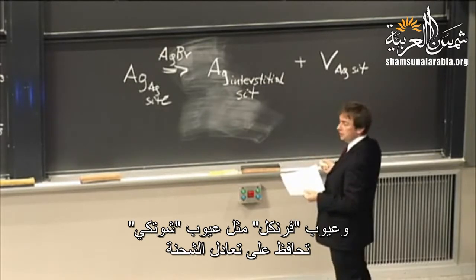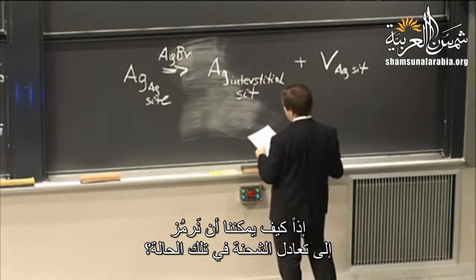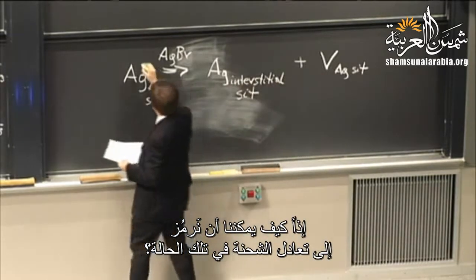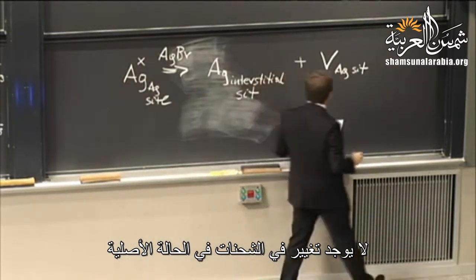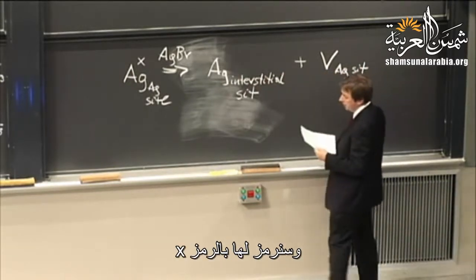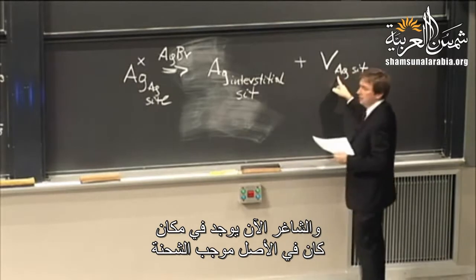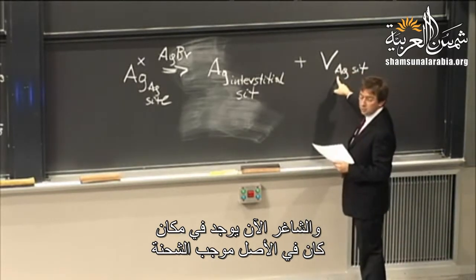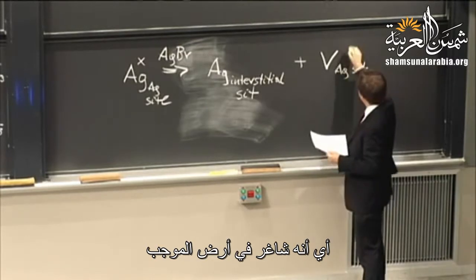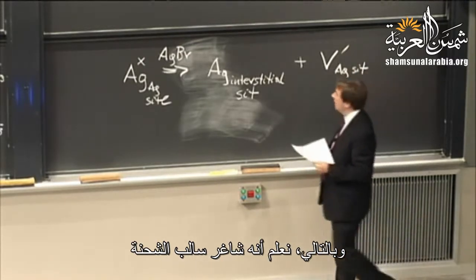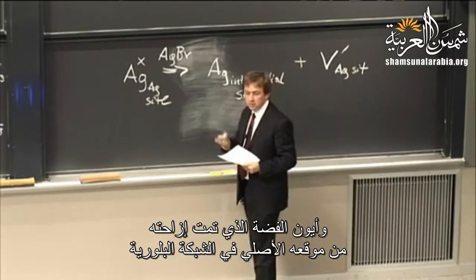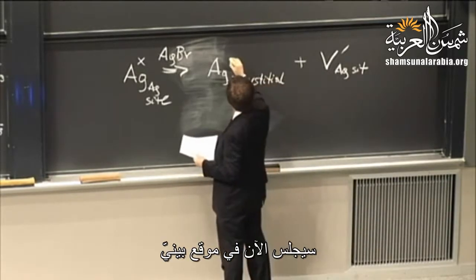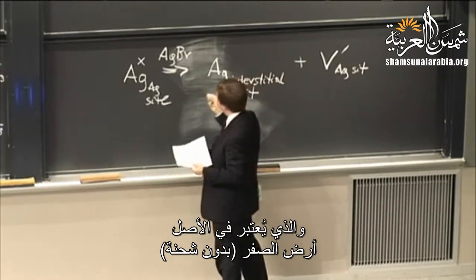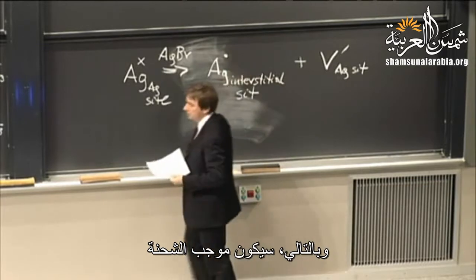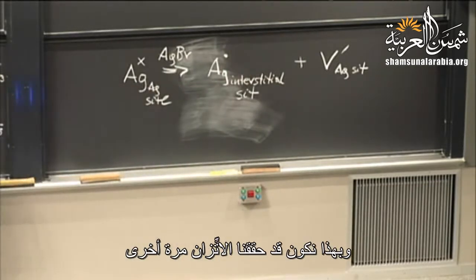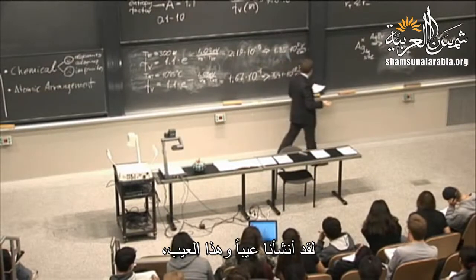Frenkel defects, just like Schottky defects, preserve charge neutrality. So how do we actually mark down charge neutrality in this case? Well, there's no change in charges in the original state, so we'll just mark that with an X. And the vacancy is sitting in a place that used to be positive, right? So it's a hole in a land of positive, so we know that this one's going to be negative. And this silver ion, which was displaced from its original lattice site, is now going to be sitting in an interstitial site, which was originally a land of 0. So this one's going to be charged positive. And now we've balanced, once again, this reaction. We have charge neutrality. We've created a defect.